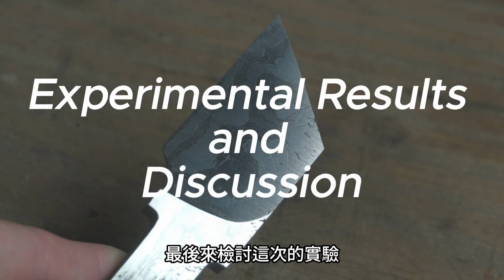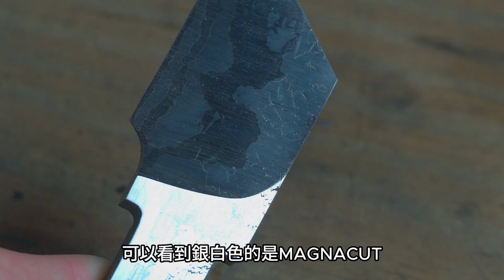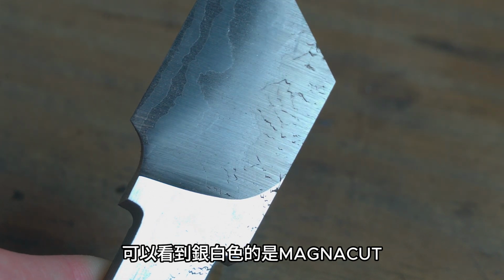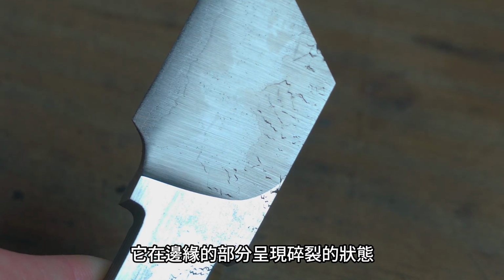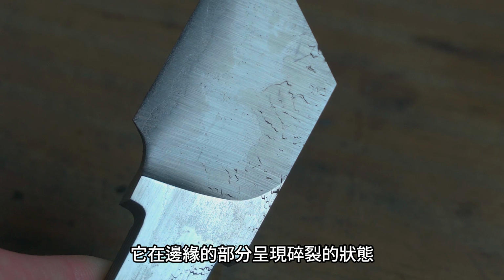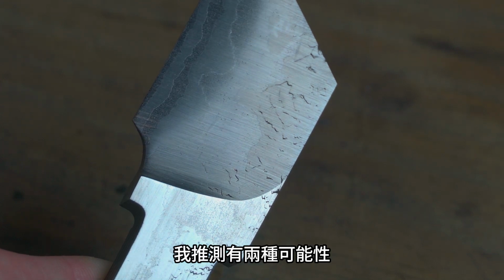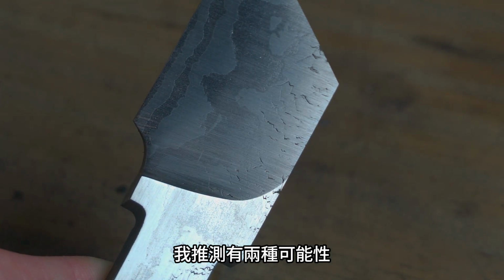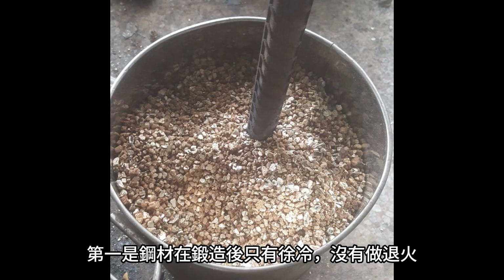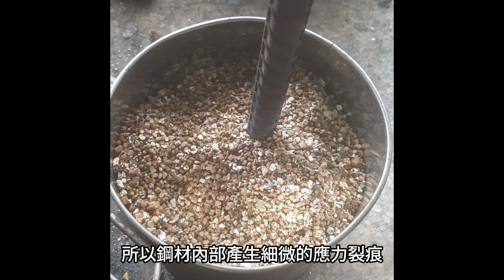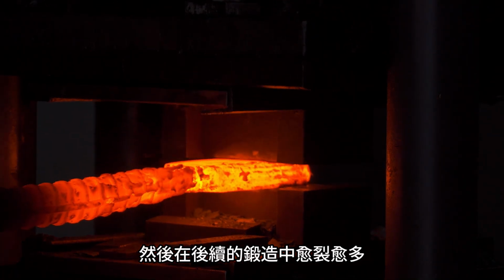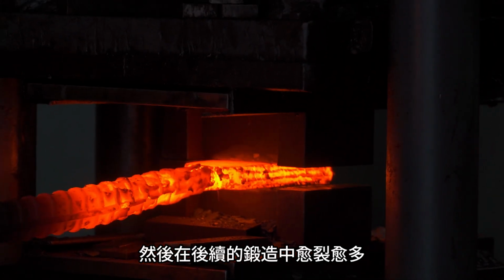Finally, let's review this experiment. You can see that the silvery part, which is MagnaCut, shows signs of cracking along the edges. I speculate that there are 2 possible reasons for this. The first is that after forging, the steel was only slowly cooled and not annealed. As a result, microstress fractures may have formed inside the steel, which then expanded and worsened during subsequent forging.